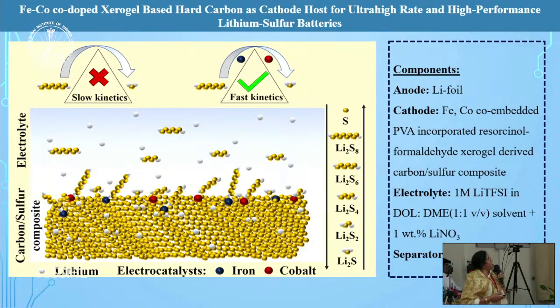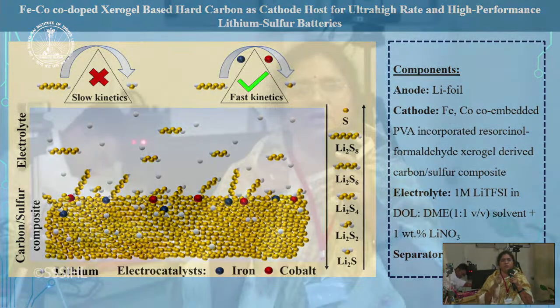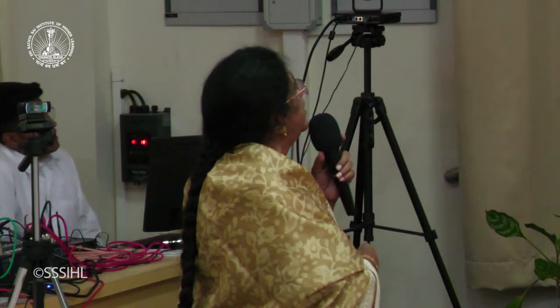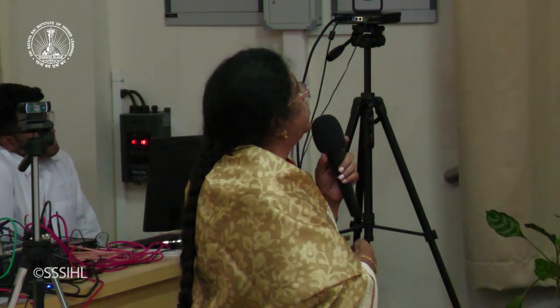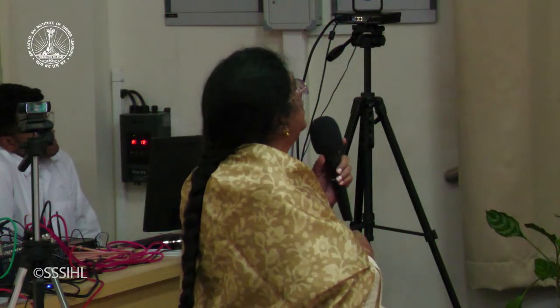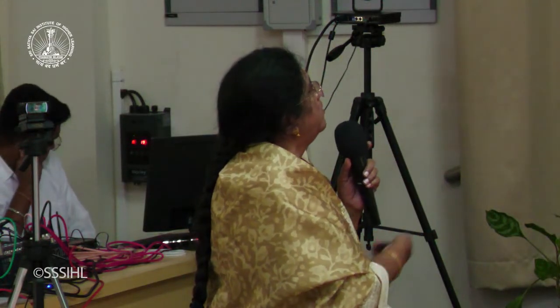And then what we have done is, I just mentioned, we have used nanoparticles of iron and cobalt into carbon, and we have used a chemical process. So here it's all constant. There is no problem. Batch to batch, it was giving perfect performance. And then we have tested the electrochemical. Oh, so this is the TEM image. You can see those metal nanoparticles embedded into carbon.